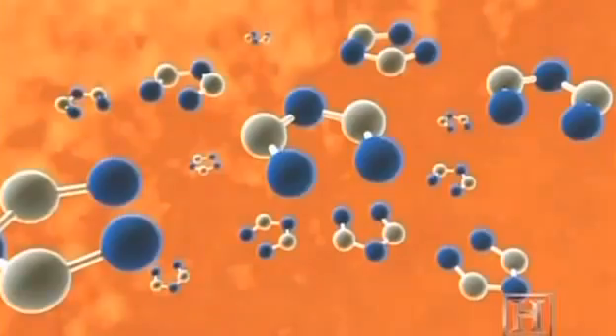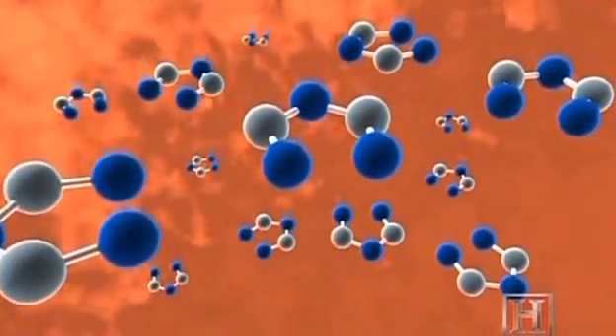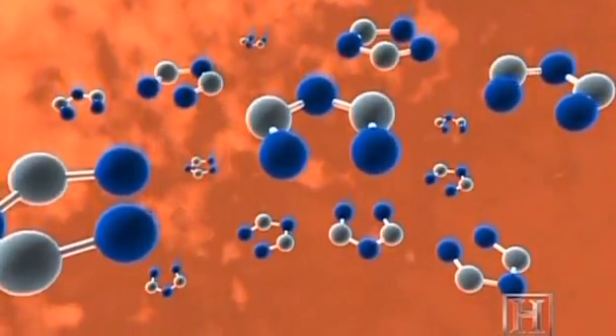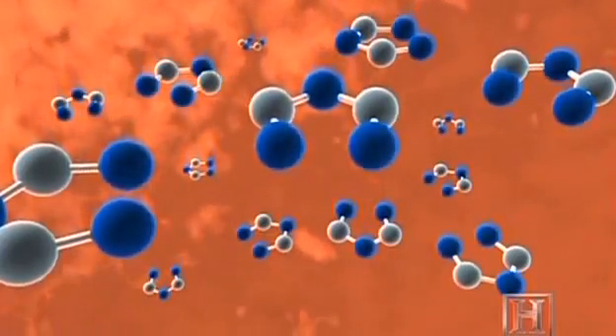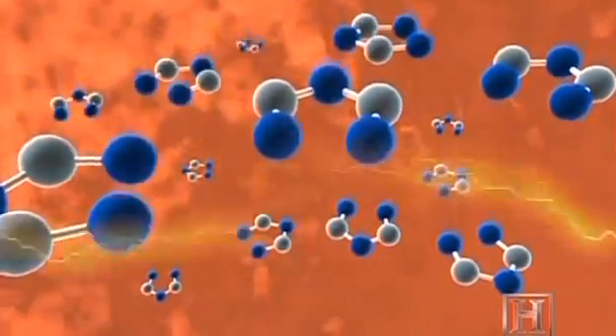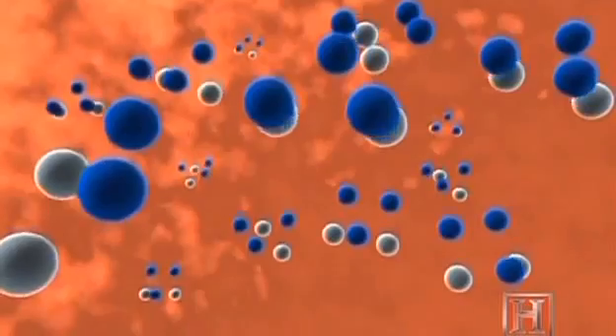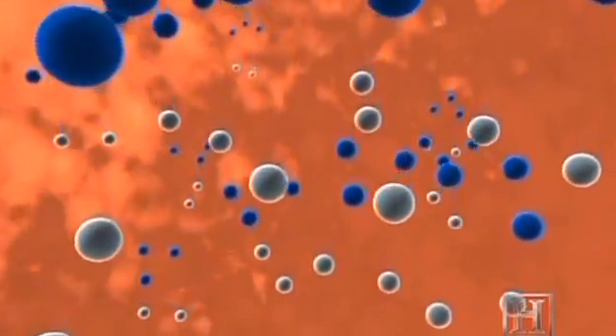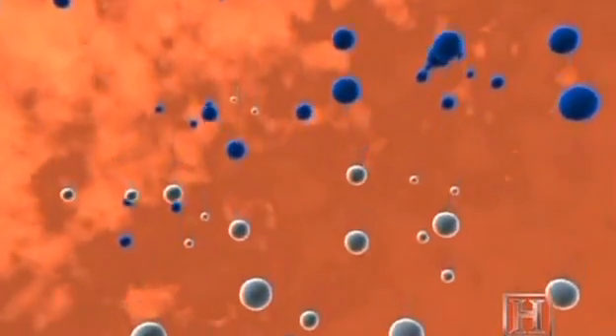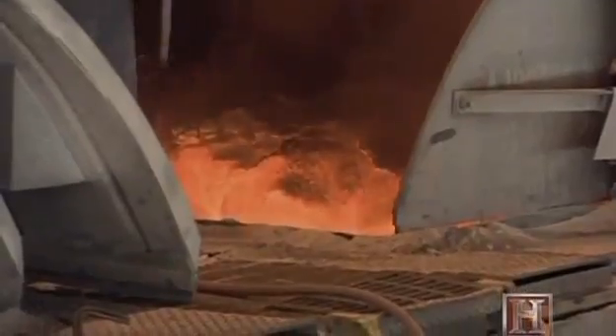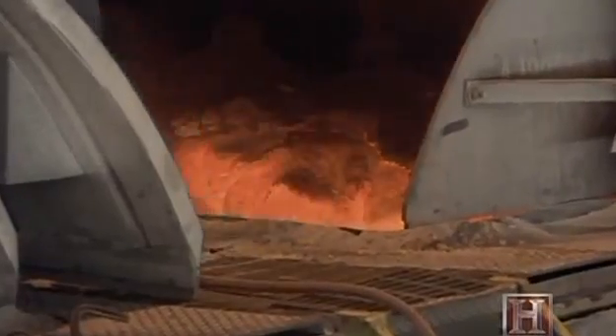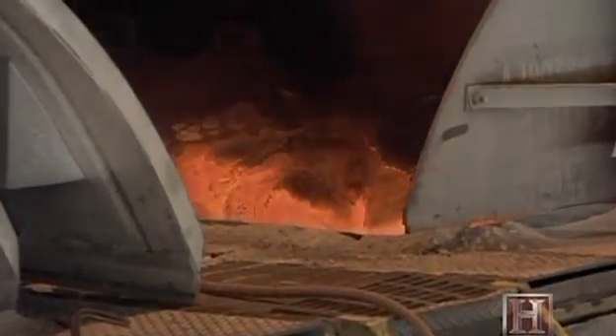The aluminum oxide molecules filling the bath contain 2 aluminum atoms and 3 oxygen atoms. The electric current breaks the bond and forces the atoms apart. And in that process, you're making liquid metal. The metal is a little bit denser than the bath. It settles to the bottom of the pot, and then carbon dioxide bubbles are given off. But the process isn't over yet. Workers then have to extract the molten aluminum from the pots and turn it into a solid.